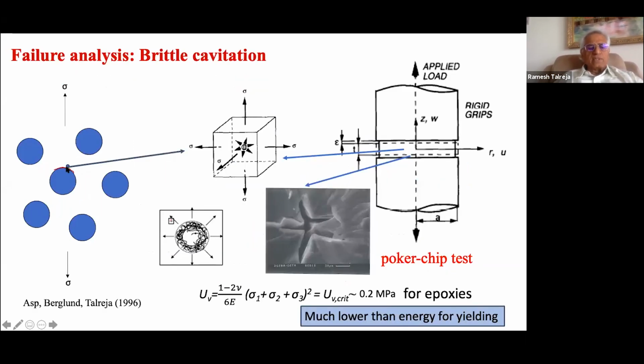Okay, so here back to this particular point. Here's what happens. The cavity forms here. And we devised back in 1996 a method called poker chip method, which was actually taken from some research in rubber by Gent. Anyway, the important point to mention here is that there's a method to independently assess and find the critical value of dilatational energy density, which will cause this cavity. And this cavity is surrounded by a brittle region because there's no shear, and therefore it expands like, should I say, burst opens, so to speak.